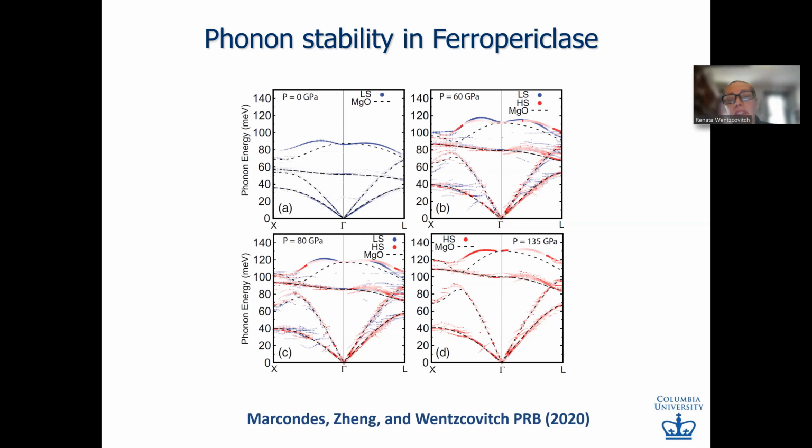This is just 3 mole percent of iron, which means it's an isolated iron. We also have results with higher concentrations of iron, irons far from each other, second neighbors, to understand what can produce phonon instabilities and whether my thermodynamics is correct or not.